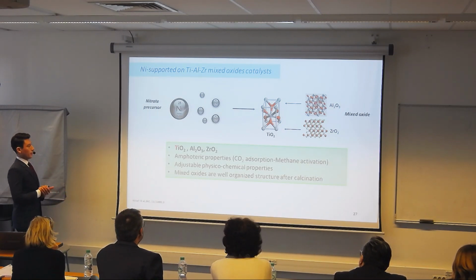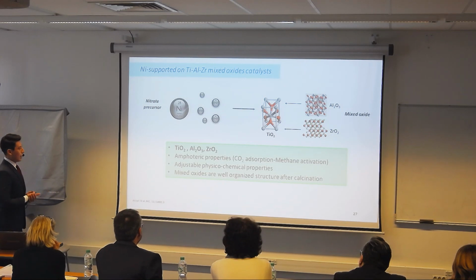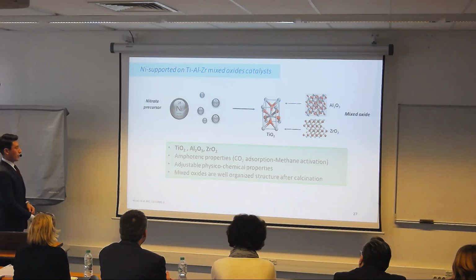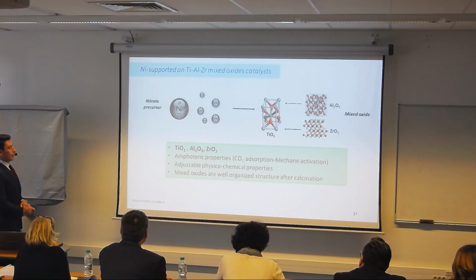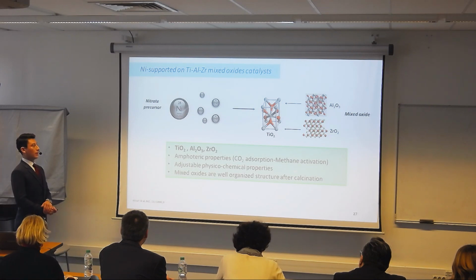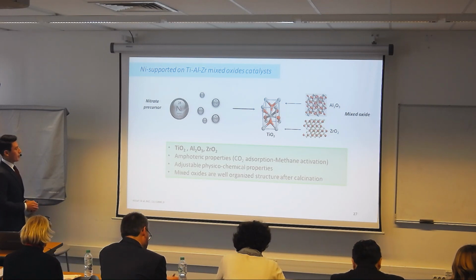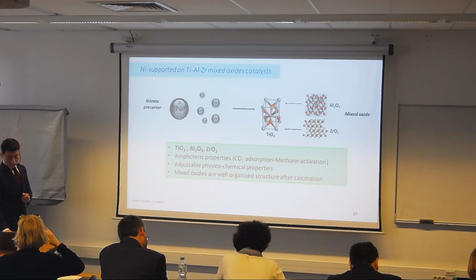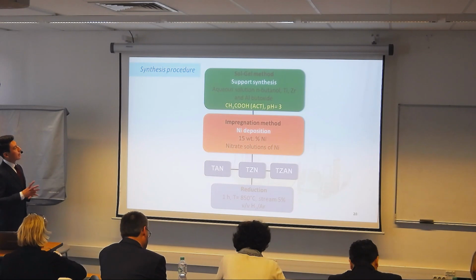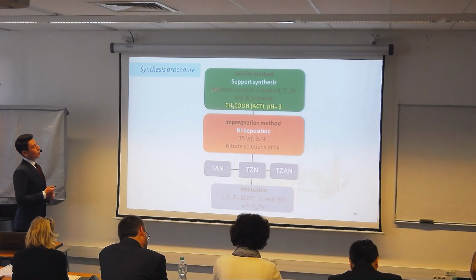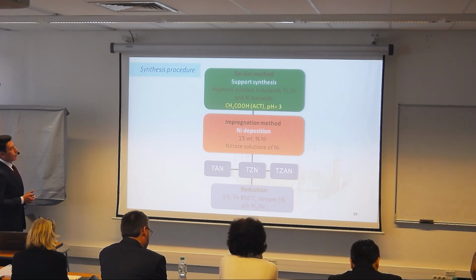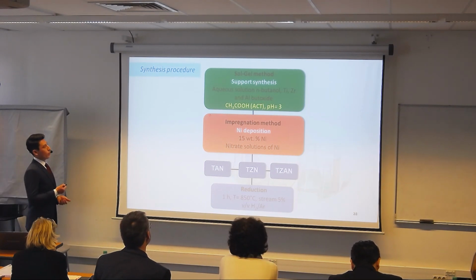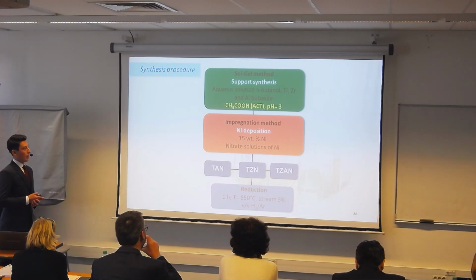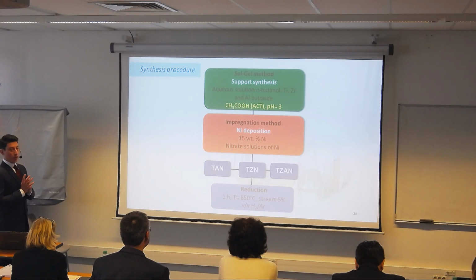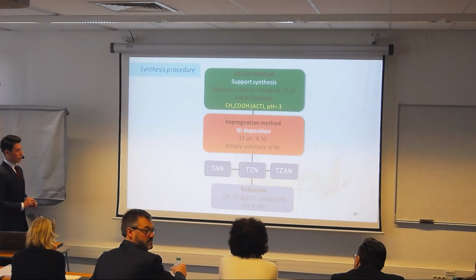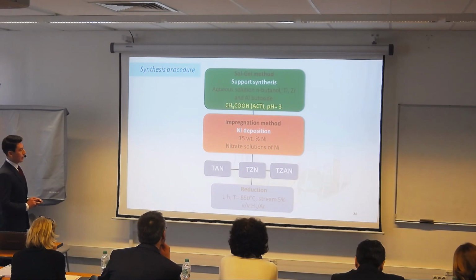Because titania, alumina, and zirconia have been very widely reported as amphoteric supports, since they can adsorb CO2 and they can also activate methane. We can also adjust these properties, and in the end they also have very high stability. These supports were prepared by the sol-gel method from an aqueous solution of different butoxides, and we stabilized the solution at a pH of 3. After the support was prepared, we deposited the nickel by the impregnation method. So in the end, we have 3 different catalysts.